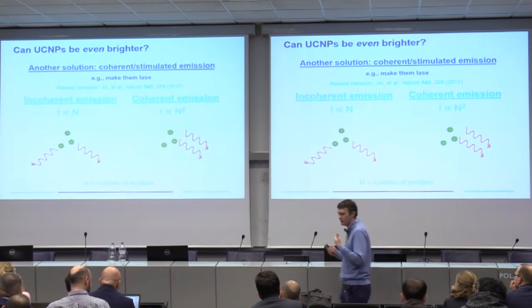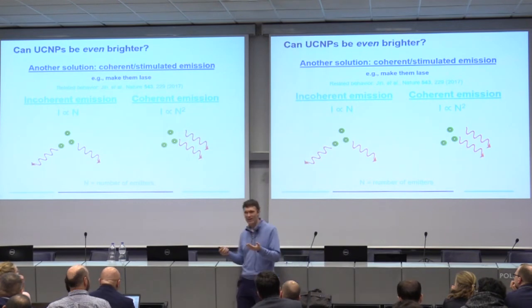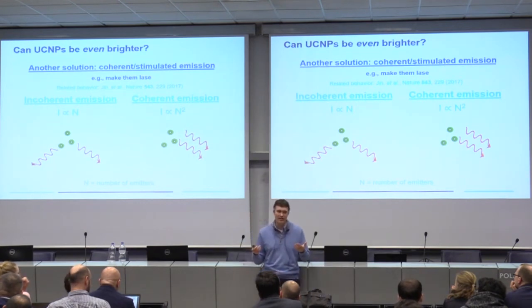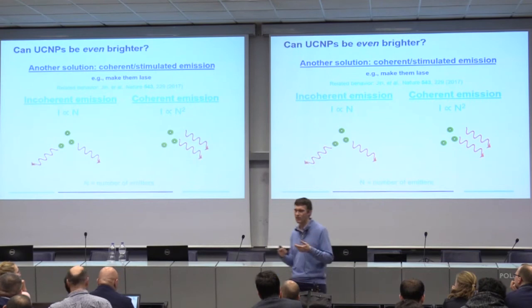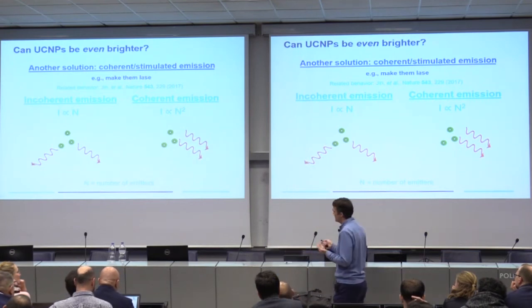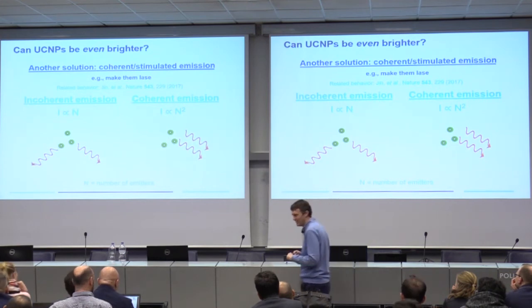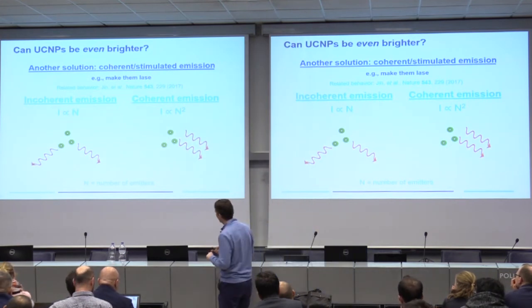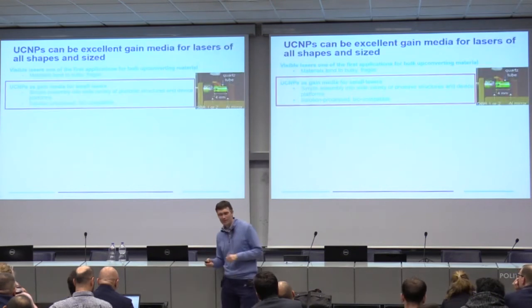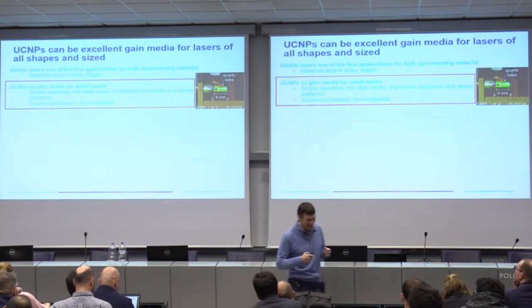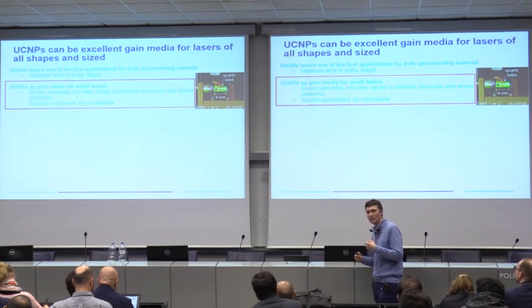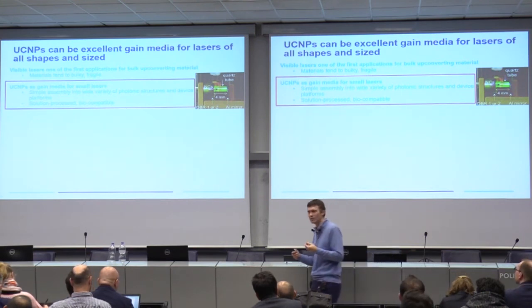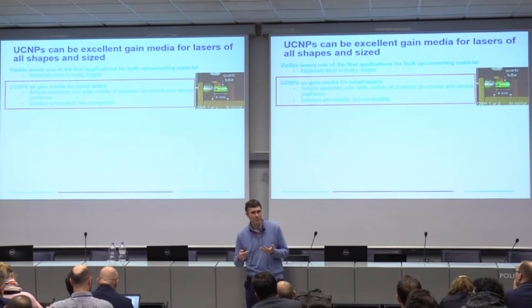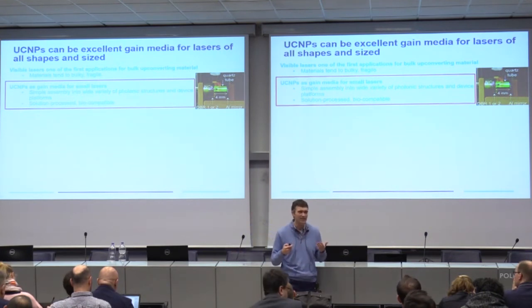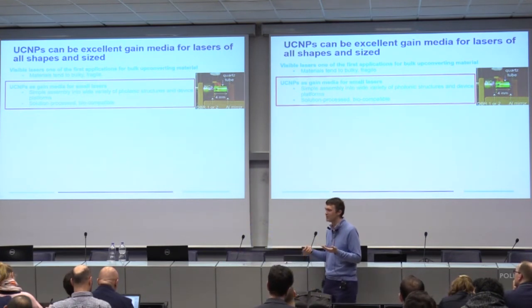And so the idea is that, as we learned yesterday in the very first talk, incoherent emission essentially has an intensity that scales as the number of emitters. But if you have a coherent emission, it scales as the number of emitters squared. And so this is a big win if we can start taking advantage of this scaling law. Now, bringing you back a decade or two, it turns out that one of the first reasons that these upconverting materials, these lanthanide-doped glasses and ceramics, were even invented was to try to make lasers.